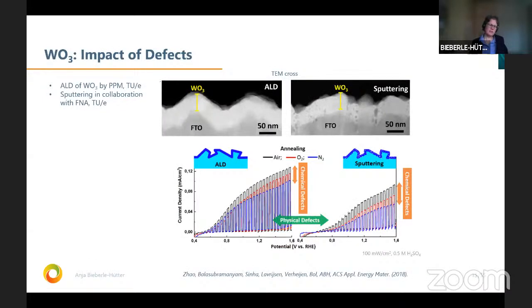Next to the iron oxide, we also have worked a lot on the tungsten oxide. Here we show the impact of defects. You see that we did sputtering and ALD of tungsten oxide films. You see in the sputtering, we have these holes. ALD looks perfect. But as I said before, when you think of really an application of these films,